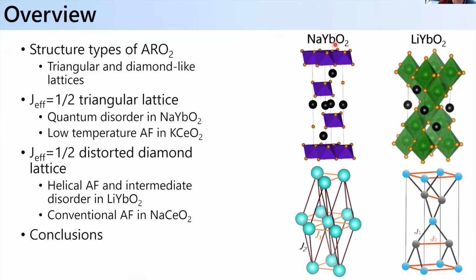So the alkali metal is sodium, the rare earth site is ytterbium. And this system forms a layered triangular lattice structure, as they've shown here, where really if I was to distill down the ytterbium magnetic sublattice of this material, this is the magnetic exchange connectivity of the magnetic system up to the nearest neighbor J1 and next nearest neighbor J2. And this is an R3 bar M type structure.